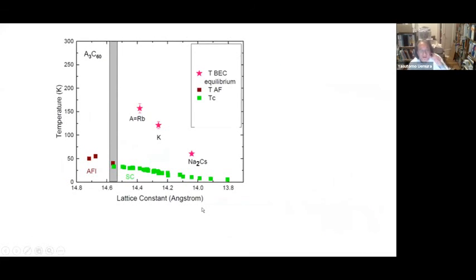Okay, so let us see the phase diagram. So for potassium 3C60, or alkali 3C60, this is the phase diagram. You have an antiferromagnetic region and then a superconducting region, which depends on the lattice constant or pressure. And we measured the superfluid density by muon spin rotation (mu-SR). If you have the superfluid density, you can calculate the hypothetical, ideal Bose-Einstein condensation temperature. For example, potassium 3C60 has a point here.